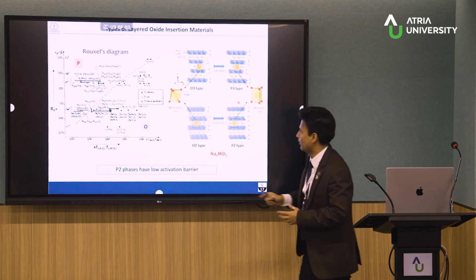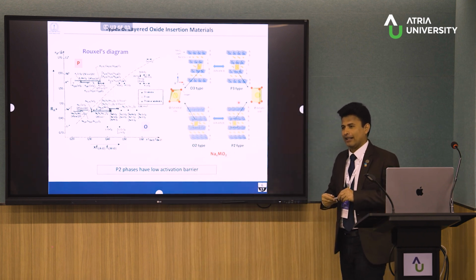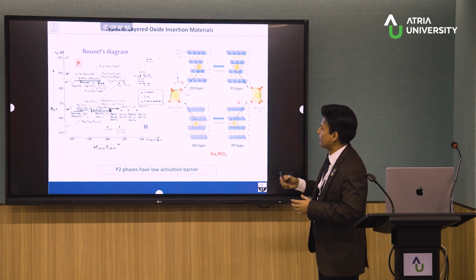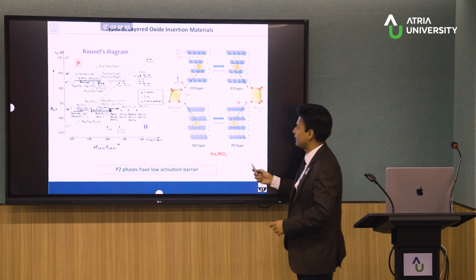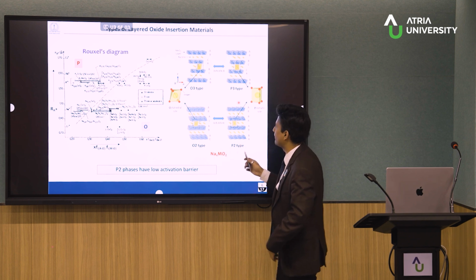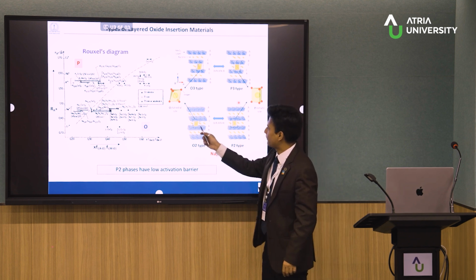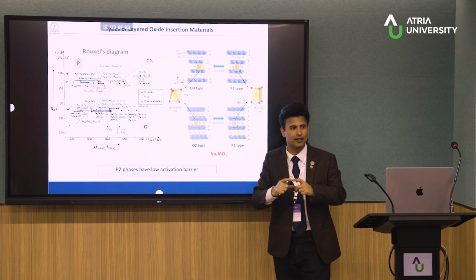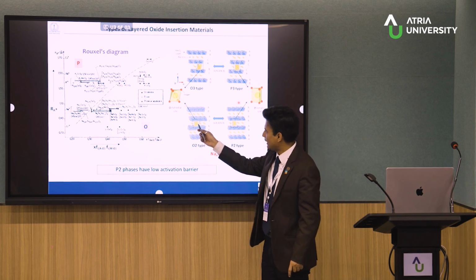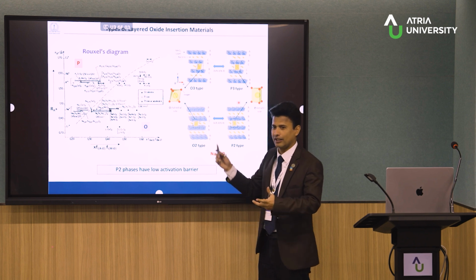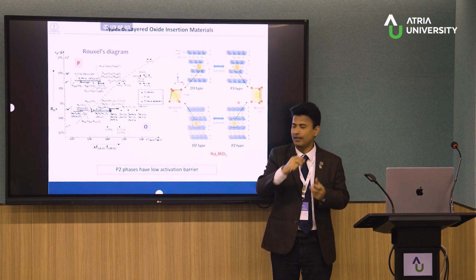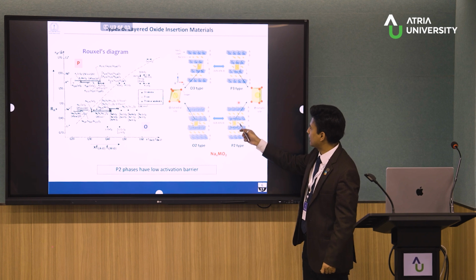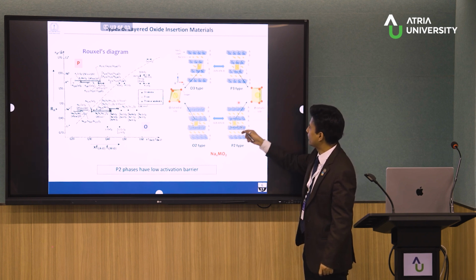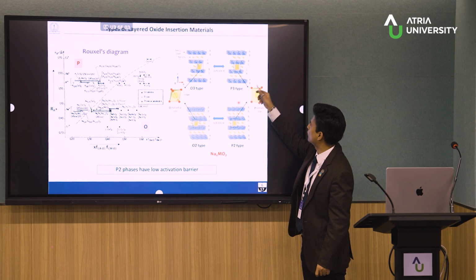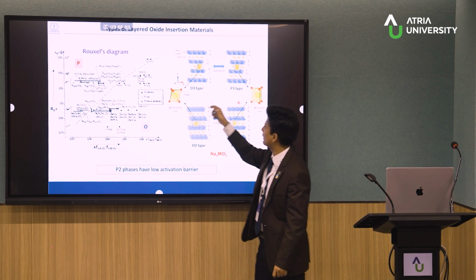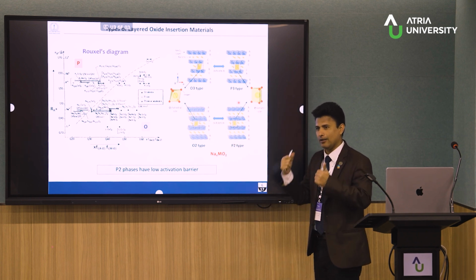So what are the P and O? All kinds of oxide, essentially, we can denote by Professor Claude Delmas notation, which is basically either O type or P type. What is that? In the case of O type, the sodium exists in octahedral coordination. So if you take the sodium and the nearest neighbor oxygen, it will look like an octahedron. And in the case of P type, if you take the sodium and the nearest neighbor oxygen in the top and bottom layer, it looks like a prism. So here is the octahedron, there is a prism. That is the P and O.